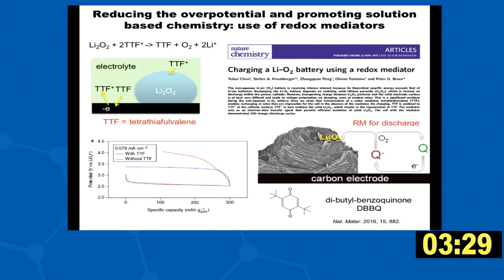So if you remember in a fully discharged battery, so this is the discharge here, where you're plotting potential versus the capacity, what you do is you form a large lithium peroxide particle. Remember, it's an insulator, and in order to oxidize this peroxide from a peroxide ion to oxygen, I've got to get electrons into the system. You can imagine that if you just do that, the only mechanism getting an electron is at that interface between the particle and the carbon electrode. But if you have a redox mediator in there, that mediator can go in and it can be oxidized itself, so tetrathiafulvalene can be oxidized, it can then go into solution, and it can go off and it can react anywhere on the surface of this particle to oxidize the lithium peroxide to oxygen. And so this is now the plot from Peter Bruce's group, where they show the discharge.